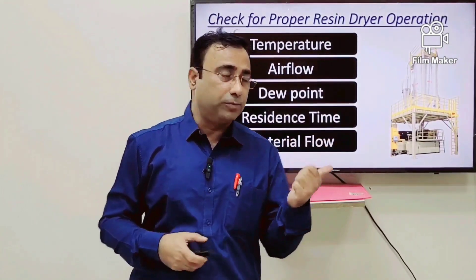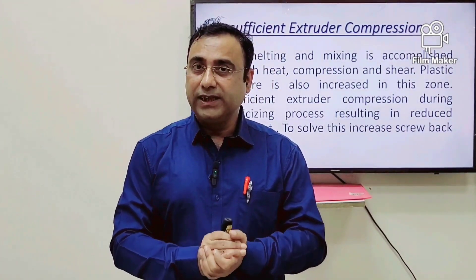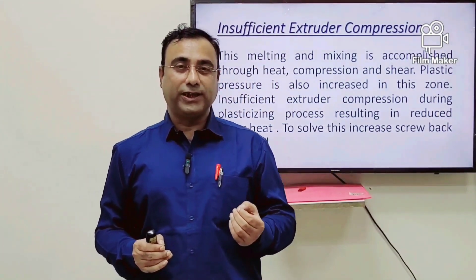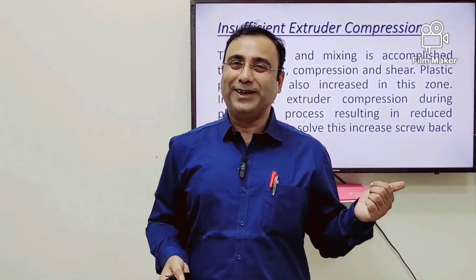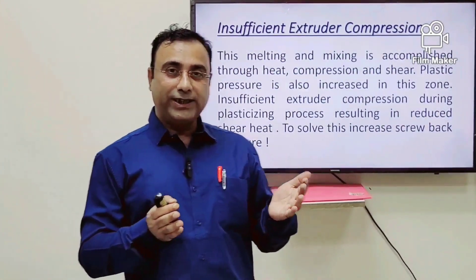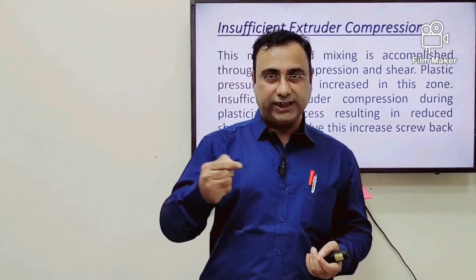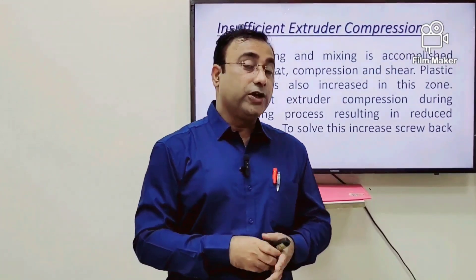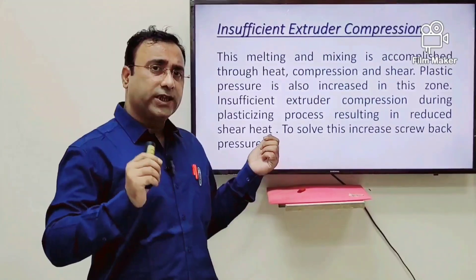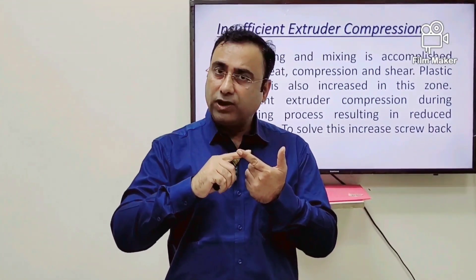The last cause to address is extruder compression. Line operators and engineers often don't understand this concept. Extruder compression is basically the plasticizing of PET material — plasticizing means it is melting and simultaneously mixing. When the screw charges, shear force is generated, producing heat, and the material is mixed. The compressed, homogeneous material should be forwarded into the mold. If there is a difference in wall thickness, that indicates the compression is not adequate.